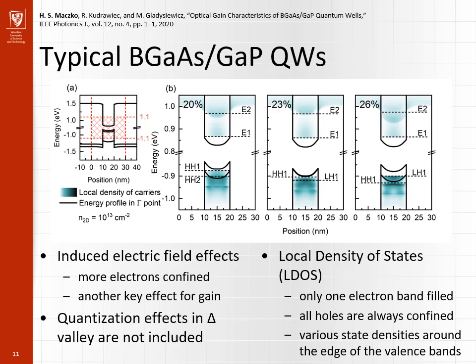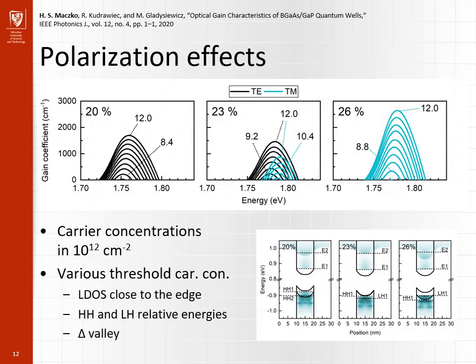Quantization effects in the delta valleys are not included in these calculations, so in real structures even fewer electrons should be localized in the delta valleys around the thin film. Also important features visible in the figures are the local densities of states of holes. The highest density close to the band edge is visible for the light holes, the effect of which will be visible in gain spectra. Gain spectra for the three quantum wells are calculated for various two-dimensional carrier concentrations.